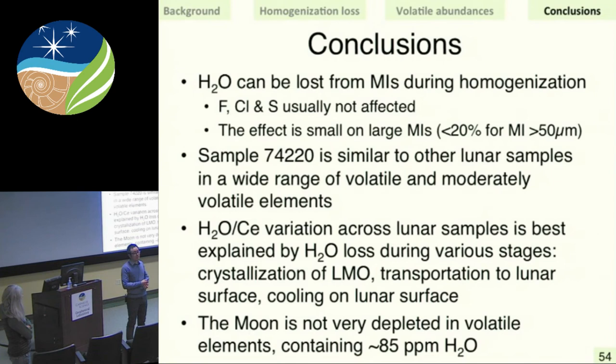And that's a hole in our study because we didn't measure carbon at all. We have two concerns for carbon. One is that our samples were measured by electron microscope, which means they have been carbon coated before, and it's very difficult to remove carbon completely afterwards. And also, we didn't have the right carbon standards for calibration. But I think that carbon is ready. It's actually more easily measurable compared to water because it has a very low background and it's very sensitive to the concentration.